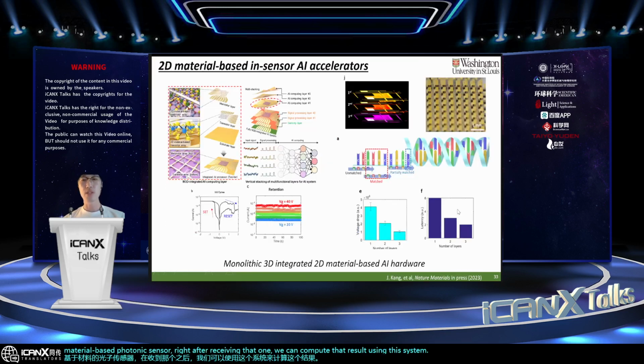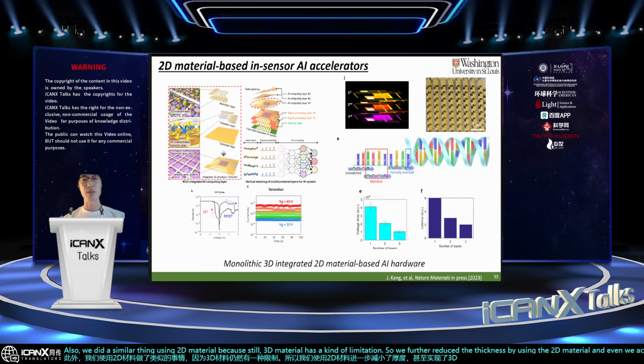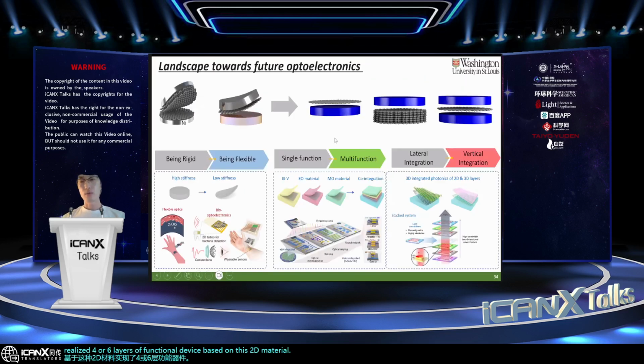Also, we did a similar thing using 2D material, because 3D material still has a limitation. So we further reduced the thickness by using 2D material, and we even realized a 4 or 6-layer functional device based on this 2D material too. So that's pretty much it. My team worked on this freestanding nanomembrane to help this transformation for future optoelectronics.